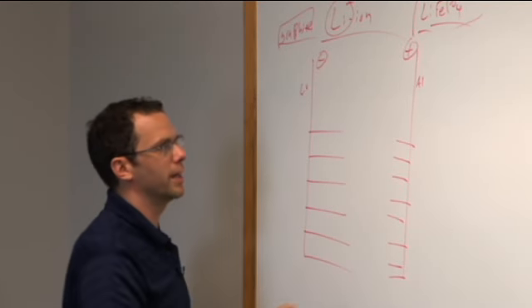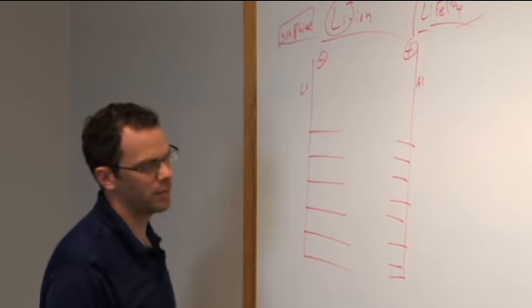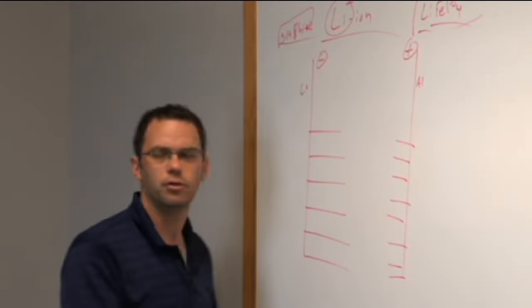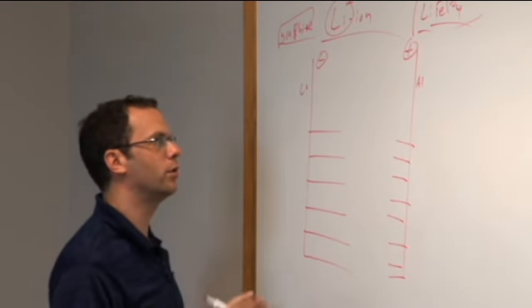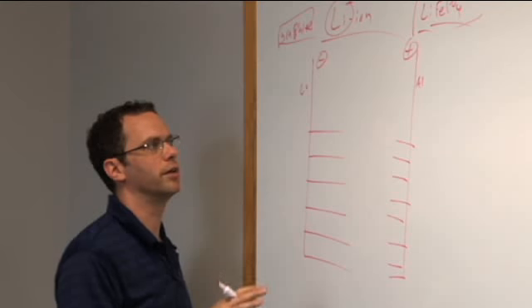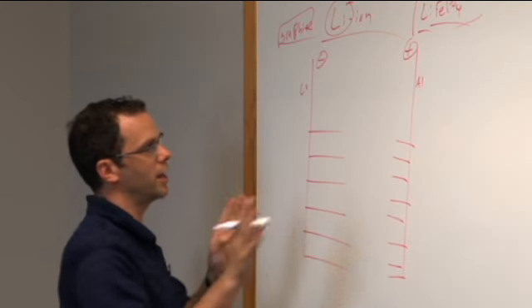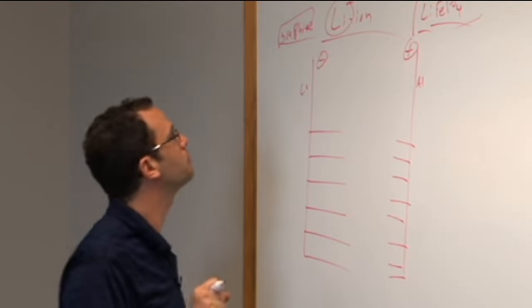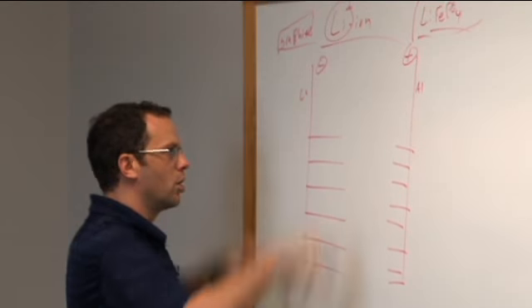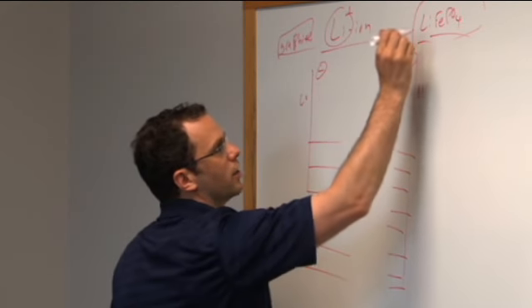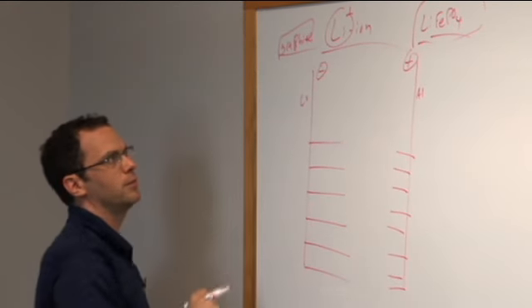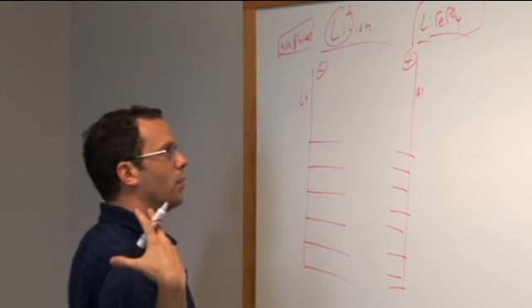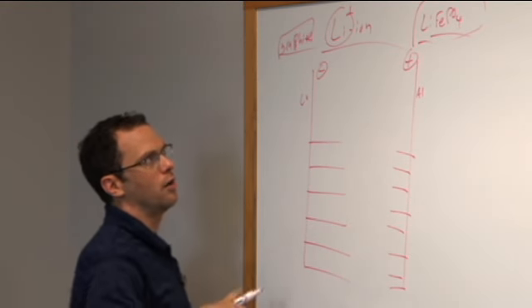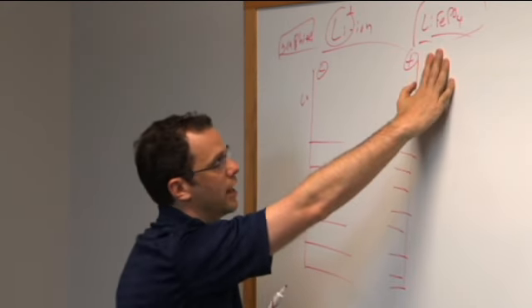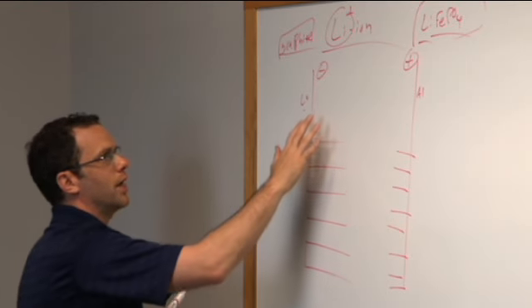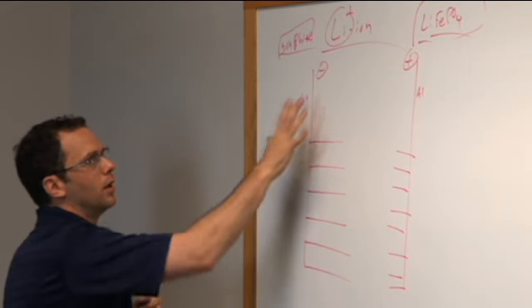And the thickness of my electrodes on any given side is somewhere between 40 and 100 microns. Typically in the 30 to 50 micron range is probably a typical thickness for the kind of high-rate batteries you guys are using. So these powders are coated on. All our lithium at the start lives in lithium iron phosphate. There's no lithium here, okay? And when the battery is fully discharged, all the lithium is back here on the cathode side, and a fully discharged battery has no lithium in principle on the anode side.